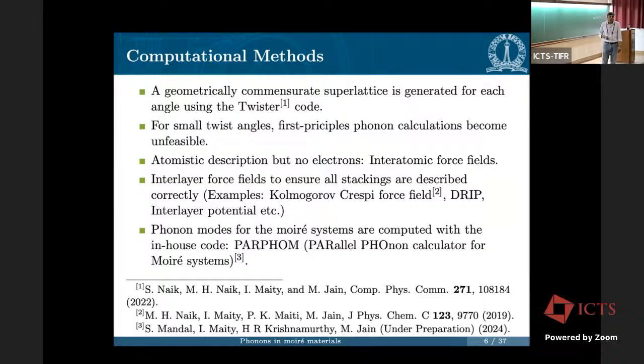The problem is, if you construct these systems, the superlattice will have tens of thousands of atoms in it, right? So there is no possibility of doing a first principles phonon calculation on the system at all. So the next best thing, there are many possibilities. One is you could write a continuum theory for this. The other possibility is you can go to these interatomic force fields, right? Interatomic force fields give an atomistic description, but there are no electrons. The electrons have all been integrated out. We only have forces on the atoms, and that's essentially all we're going to work with.